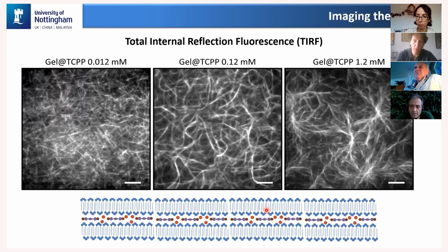So one thing you'll notice is that a lot of gel molecules in general tend to look like liquid crystals, let's say. They're kind of calamitic, long rod-shaped things that are going to come together and form lamellae. We actually had a case of a disc-like molecule, which in principle wouldn't do the same kind of thing because you could get growth in the plane of these stacks. You could get growth in all three dimensions. And we had a kind of strange morphology out of that, which we never really understood.